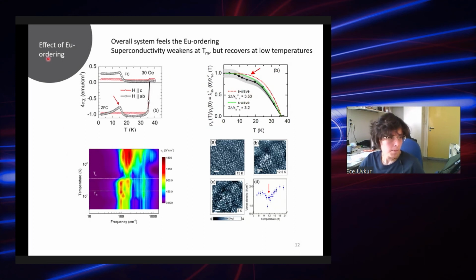Okay, so when we look at our overall results about the effect of the europium ordering, the system certainly feels the europium ordering, but the superconductivity weakens at the ordering temperature and recovers at low temperatures. So we had several indications for that, like the magnetic susceptibility, where the europium orders, but then the volume fraction recovers, and the superfluid density weakens a bit, but then recovers. Well, the overall system really feels it.